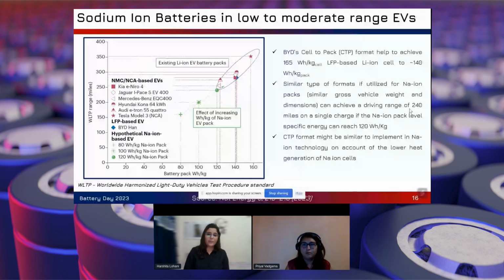So here you can see NMC and NCA based electric vehicle battery packs obviously have a very high battery pack energy density, which is greater than 250 watt hour per kg, and they have a long driving range, which is more than 280 to 350 miles. But if we see the LFP or the hypothetical sodium ion based EV battery packs, even with 120 watt hour per kg of the sodium ion pack, we can go up to 240 miles, which is very close to the LFP BYD Han battery pack.